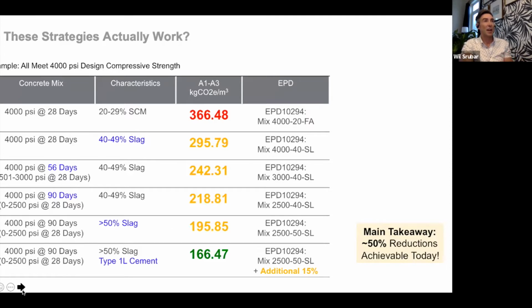the different levers that we pull, switching from 28 days, for example, to 56 days, or the differences between the first and the second row here, going to higher SCM contents with up to 50% slag, moving then to a later age design compressive strength from 56 to even 90 days, going above 50% slag, and even using a type 1L cement. Just those simple strategies that you can implement today could result in substantial, we're talking 50% reductions in embodied carbon of concrete that are really achievable today.